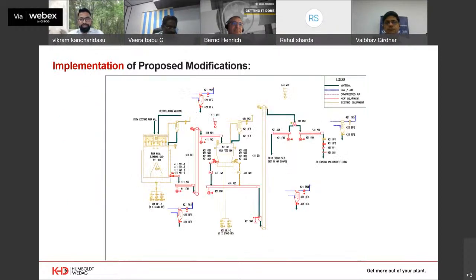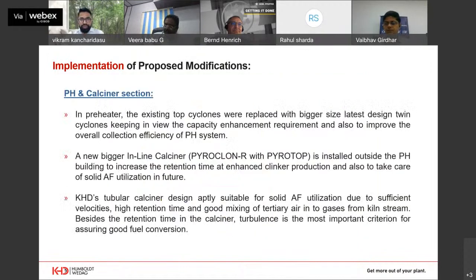Here in the flow sheet, you can see all the red color equipment have been replaced. The extraction gates from the blending silo and air slide, because the capacity was not sufficient, so we have installed higher capacity equipment. The kiln feed bin is installed in the preheater building. And then a new elevator is proposed because the capacity was not sufficient for the earlier elevator. The client has replaced the airlift system with the bucket elevator for the preheater feeding, and then air slides of higher capacity are installed for feeding into the preheater system.